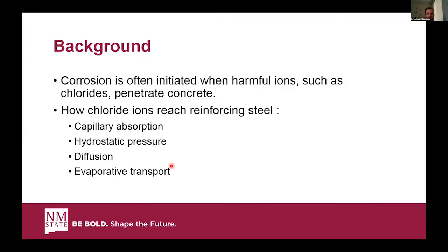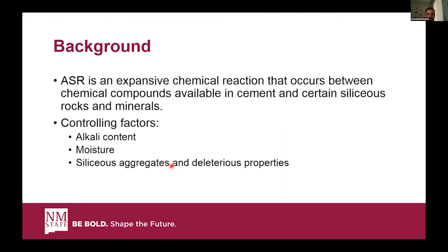We all know that when harmful ions like chloride penetrate concrete, corrosion is initiated, and it can happen through four main ways: capillary absorption, hydrostatic pressure, diffusion, and evaporative transport. On the other hand, ASR is an expansive chemical reaction that can produce some internal tensile strain that can lead to cracking and lead chloride and other harmful ions to penetrate more into the concrete. And it can be influenced by alkali content, moisture, and how siliceous the aggregates are.